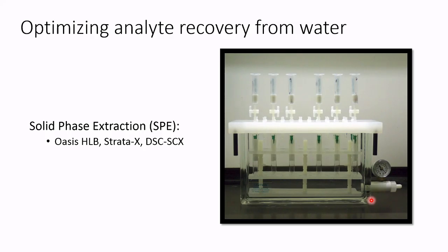Challenge, because now you're trying to concentrate things that you don't know what they are. So typically, when you're using solid phase extraction, or SPE, you would pick a solid phase cartridge. So these are these cartridges right here, this tiny little bit of solid phase. Your sample is run through these cartridges, and these little solid phase areas here will retain the analyte in your sample. And then afterwards, when your sample has passed through, you take a solvent of another kind to elute that and release those into your sample tube.